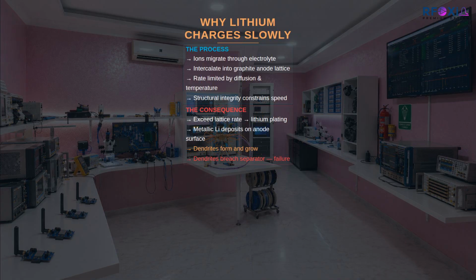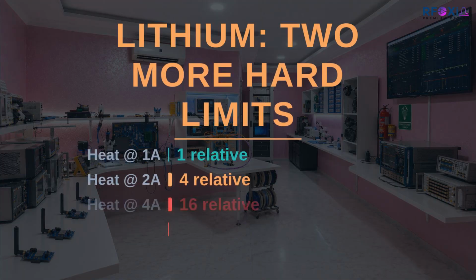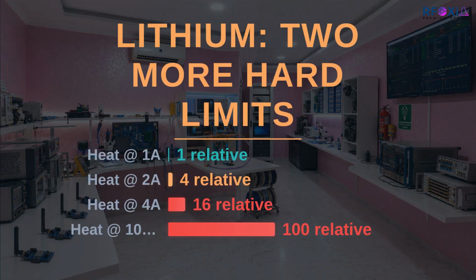Second, the charge acceptance of a lithium cell drops dramatically as the cell approaches full charge. The constant current phase that begins a charge cycle gives way to a constant voltage phase where current tapers, sometimes for longer than the initial CC phase. This is not a charger limitation. It is the cell protecting itself from overvoltage damage to the cathode. You cannot simply increase current to speed this up. The cell will not accept it without accelerated degradation.